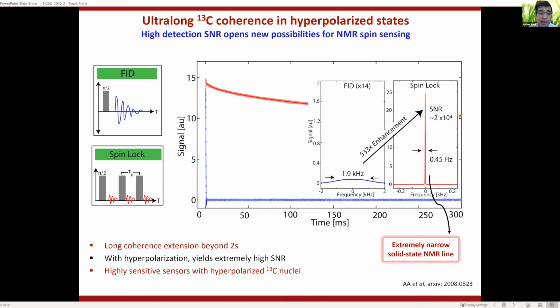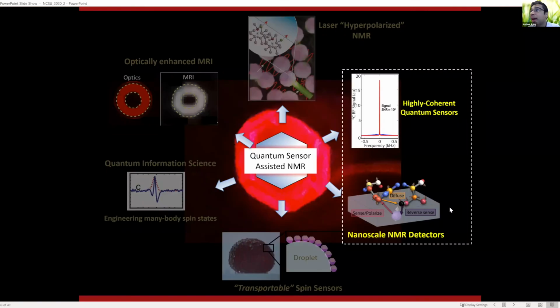And I should mention that this is not very special to diamond. It's actually quite a general property in solids, and this was investigated back in the 70s and 80s. But what's special here is that we can marry it together with hyperpolarization in a nanoparticle or microparticle platform. So it allows you to obtain a very high fidelity NMR signal of these nuclear spins, which are usually quite inaccessible, but because you can polarize them with light and you can see them with these enhanced readout techniques, they become amenable to using them for some physical tasks. So the protocol itself is a variant of some older ideas, but applied now to this newer system where you can get very high single shot. So this is a single shot SNR, about 1 milligram of diamond. So you can ask what you can use this for.